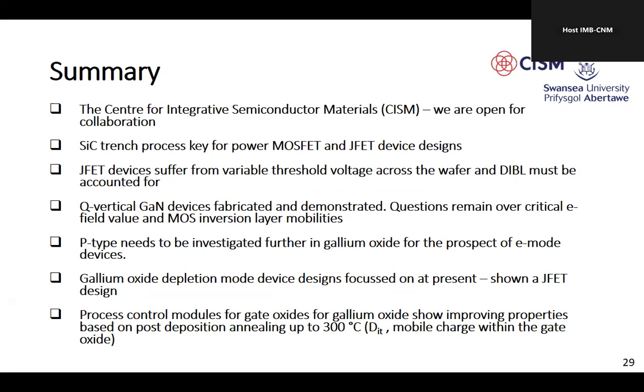I introduced some JFET technology, and the main conclusion from that work is that variable threshold voltage across a wafer and drain-induced barrier lowering must be considered for JFET technologies in silicon carbide, right? We demonstrated some vertical or quasi-vertical gallium nitride. Questions remain over the actual critical field of the layers, but initial results were very promising in terms of channel mobility for sure.